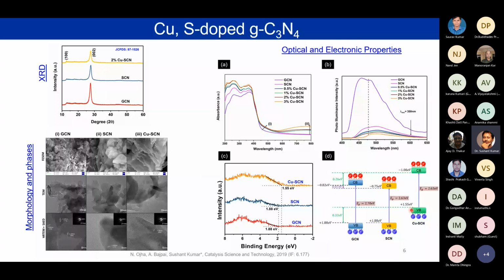Initially, the graphitic carbon nitride valence band is somewhere here, and the SCN is here, and then the copper SCN. If this is the band gap of this photocatalyst, the conduction band has gone up. That means the reduction ability from carbon dioxide to carbon monoxide or methane, the thermodynamic efficiency, becomes higher for copper SCN. And that is a great thing. Thermodynamics says that yes, copper SCN is very good. Let's go and check the kinetics.